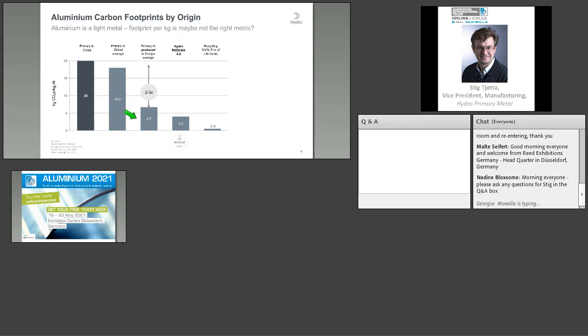If we then move to the carbon footprint of primary aluminium produced in Europe, it's 6.7, and it has actually gone somewhat down in recent years due to a higher share of renewable energy as a basis for the production. And it's actually 2 to 3 times lower than the global average. If we go to aluminium based on renewable energy sources, and I use our own green aluminium brand as an example here, we call Hydro Reduxa, which is based on hydroelectric power, it will have a carbon footprint around 4, being 4 to 5 times lower than the global average.